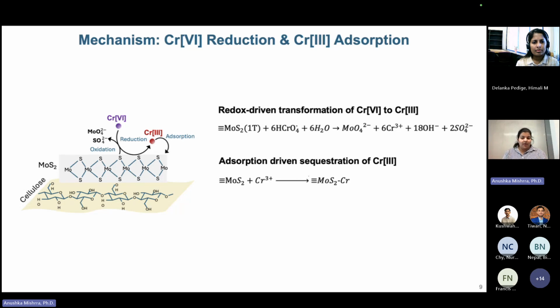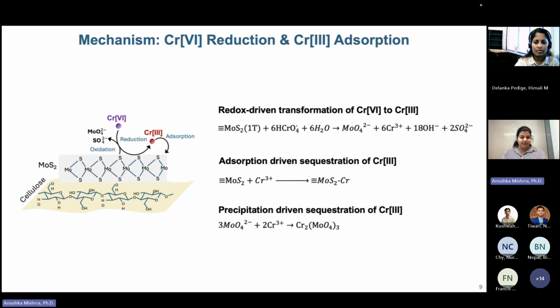We also have another method of sequestration. Once you have chromium-3, which is positively charged, whereas chromium-6 exists as an oxyanion so it's negatively charged, this chromium-3 can interact with MOS2 because MOS2 actually has a negative surface charge around it. So we think adsorption can also take place for sequestering some of the chromium-3 on the surface that we saw through XPS.